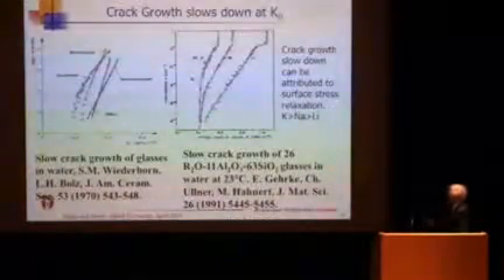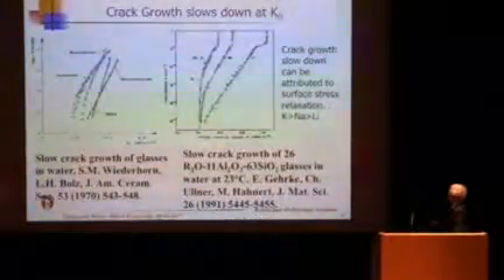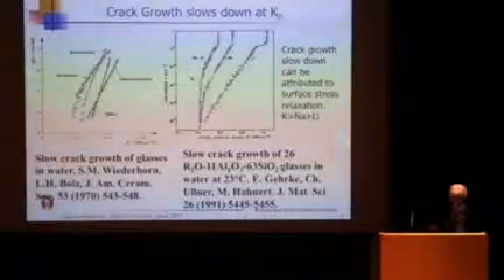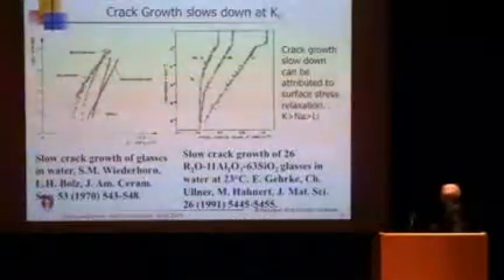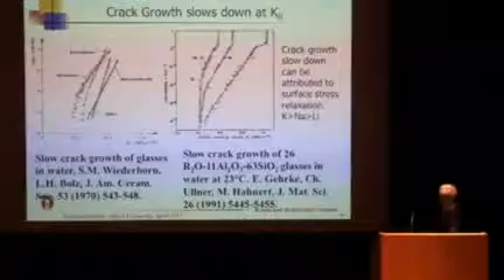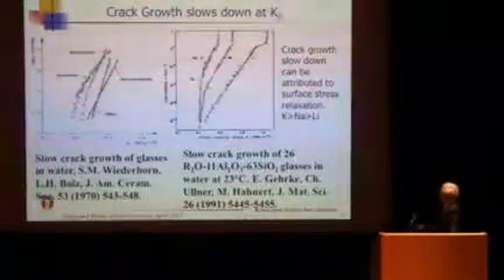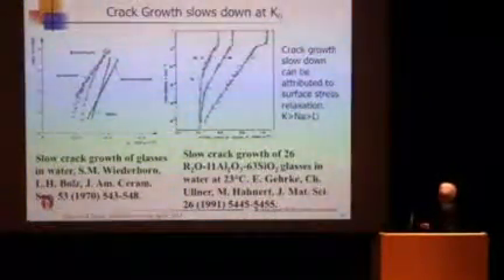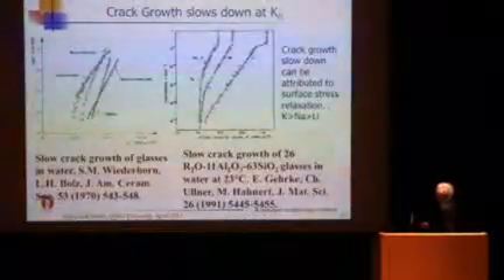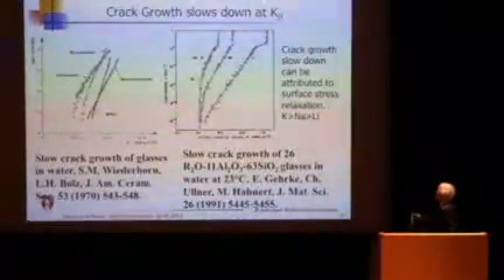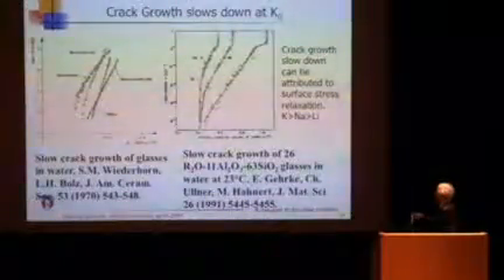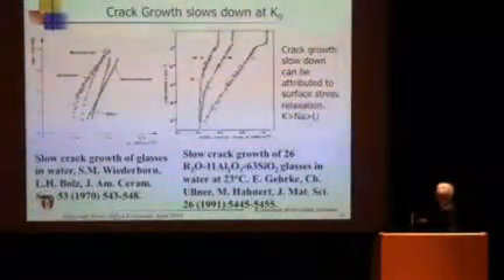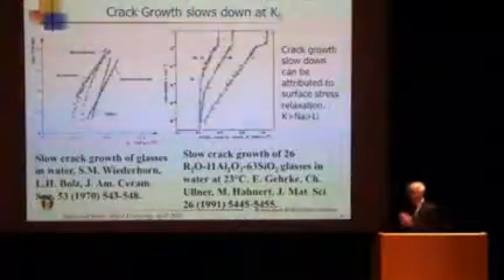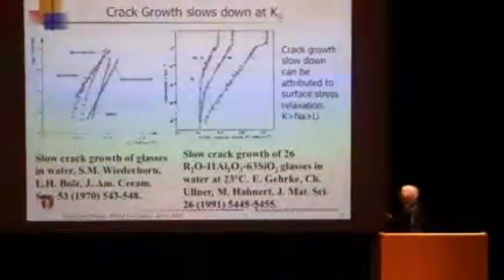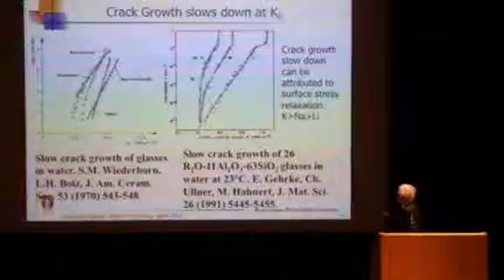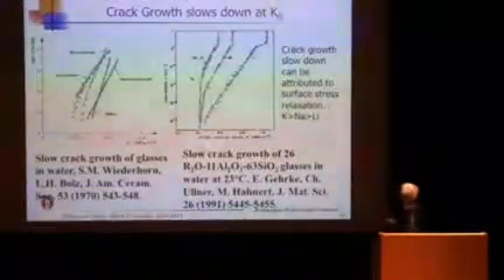This somewhat related phenomenon to fatigue is slow crack growth. This was pioneered by Sheldon Wiederhorn and his collaborators at NIST in the late 60s and 70s. They measured a variety of different glasses and applied stress, stress intensity to be precise, measuring the crack growth rate as a function of stress intensity. If you apply higher stress, of course, the crack grows faster. So they normally have this slope. And this is highly sensitive. This was promoted by moisture.